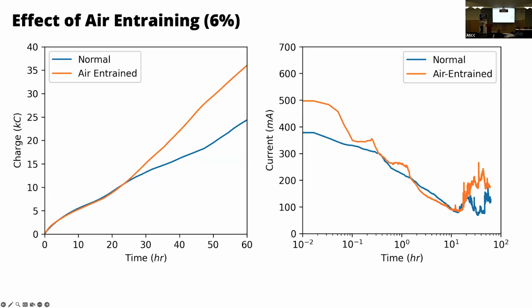If you see the response over here, the orange line is higher than the blue, which means that in the air entrained concrete, the corrosion is going to be more accelerated. So corrosion is going to happen faster. That makes sense because it has more pores inside of the concrete.